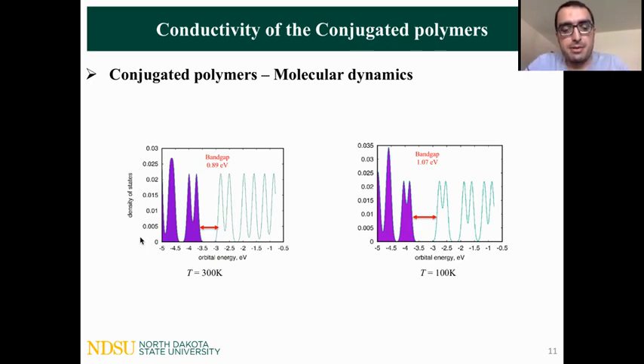Also, I want to show some brief results from the molecular dynamics at different temperatures, as others discussed. For this conjugated polymer, we compare the DOS for two different temperatures, room temperature and 100 Kelvin. And you can see that by decreasing the temperature from 300 to 100, there is an increase in the band gap. That means a decrease in the conductivity. Next, please.